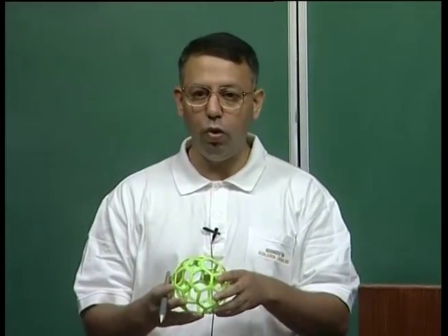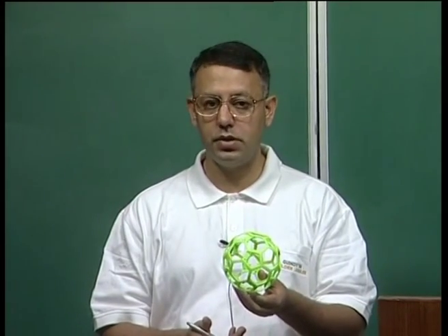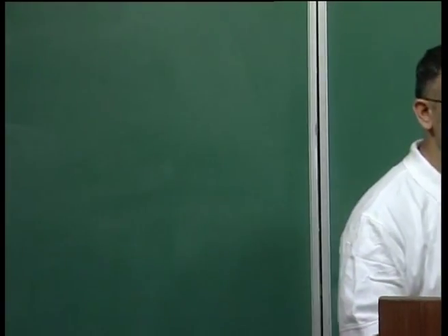So, depending on the definition of the packing fraction, and of course, I am using a definition now that the carbon volume occupied by carbon atoms with respect to the total volume available in the crystal, then this will be a very poor packing of atoms in space. In other words, even though this is a FCC crystal, this is definitely not a close packed crystal. So, this is further emphasizing some of the points we had already considered during our earlier lectures.